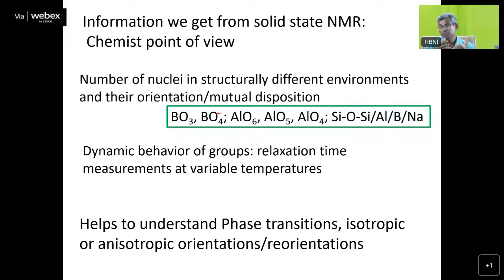For example, if you take alumina, it exists mainly in two forms, alpha form and the gamma form. Beta form is quite different. It contains some sodium ions also. The alpha to gamma transition leads to change in the aluminium environment.